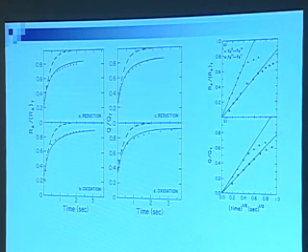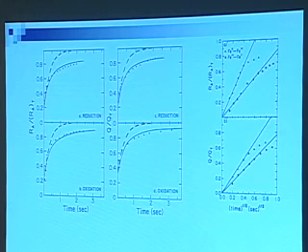Okay. How little a secondary process would you live? I mean, that shows you that within probably 5%. It doesn't show you within. Oh, actually, we figured it was within probably 1%. We could detect a change. We had done a fair amount of this, doing steps here and looking at spectral changes, so we thought we were good to 1%. So yeah, if it's happening, and it probably is happening at some low level, to be honest, but it's less than 1%.